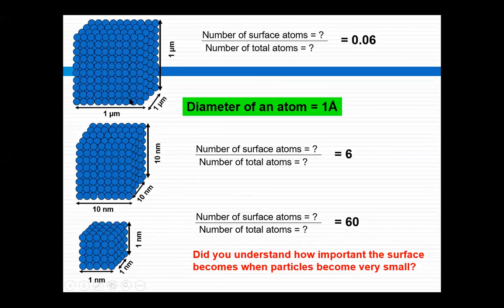In the case of a 1 micrometer size particle, you have only 0.06 fraction of the atoms on the surface, which means negligible. If the particles are of millimeter size, then it is much lower than this. So compared to 100%, you have very little. Now, in the case of 10 nanometer size, you have a 6% fraction, which means 6% surface atoms on the surface and the remaining 94% in the core. If the size is 1 nanometer, you will get 60%.